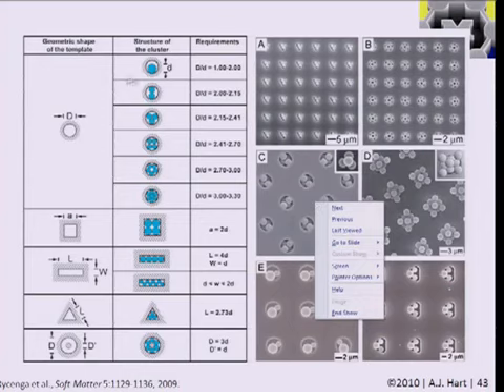What they showed is that you can geometrically relate simply the shape and size of the template to the resulting packing that occurs. So, for example, if you had particles with diameter d, say 1 micron in diameter or 1 unit in diameter, if you had a cavity that is between 1 and 2 microns in diameter, then you'll only get 1 particle in the hole because another particle won't fit. Also, of course, the depth of the hole is between half a particle high and 1 particle high. It's not deep enough to hold 2 particles.